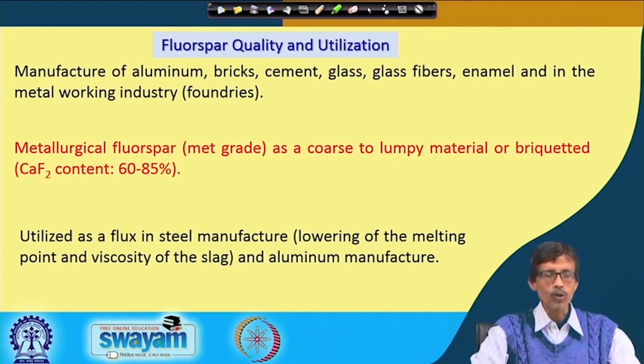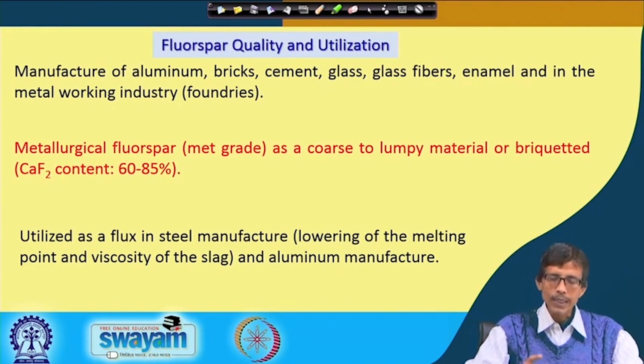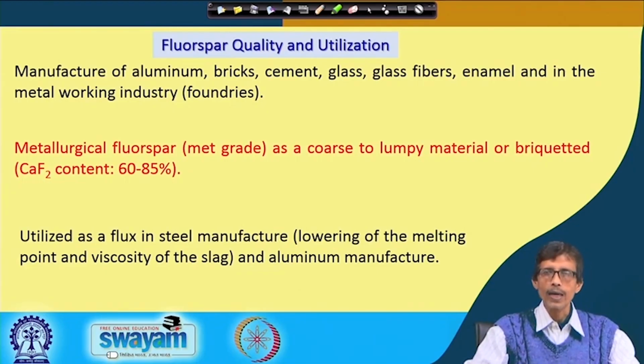So, lowering in both of these two cases, the melting point as well as the viscosity of the slag, it is very easy to remove the slag material from the pure iron material, that is the molten iron we have in our hand. So, if the slag material is lighter than your molten iron, it will float at the top of the molten iron. So, you can have some duct or some exit pathway through which the slag can be removed.